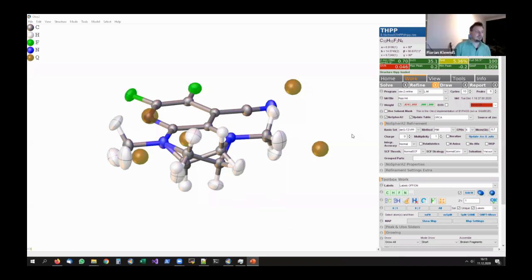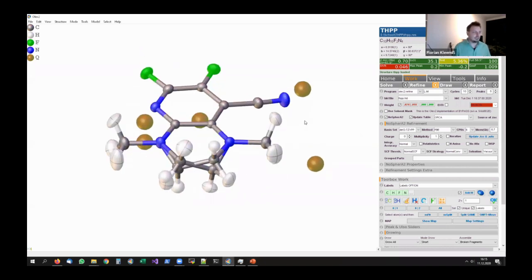The scattering factors are completely independent of your ADPs. So whether you use anharmonicity or not, whether you use isotropic or anisotropic displacement parameters does not affect the generation of the TSC file. However, the F-calcs are generated using these ones. So if you use anharmonicity, you could improve the model. But this feature is still very, very experimental, and therefore I would recommend you get in closer contact with the OLEX people to discuss in further detail.